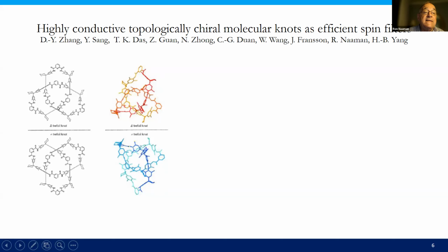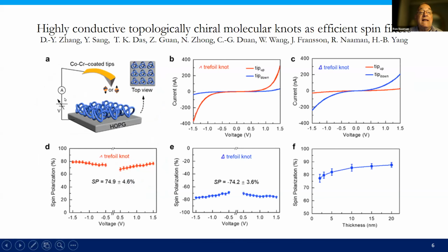Because here in these parts of the molecule, there are electrons that are delocalized. And we use this magnetic contact AFM to measure the spin-dependent current. Basically, we put the molecule on the surface. We have a tip of an AFM here. We can magnetize the tip either with the magnetic field up or down, as you see here, and we measure the IV curve. And here you get it, and you see very clearly a big difference between the current when the tip is magnetized down, namely the north is pointing towards the molecule, versus the tip magnetized up.